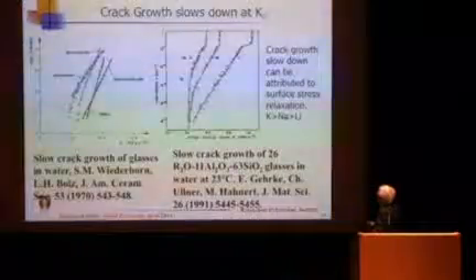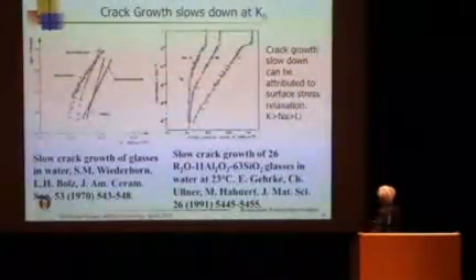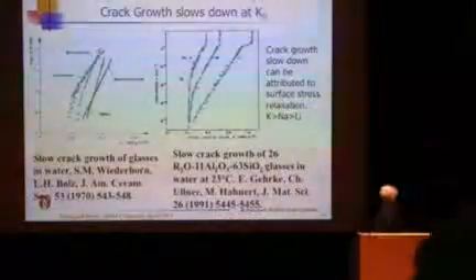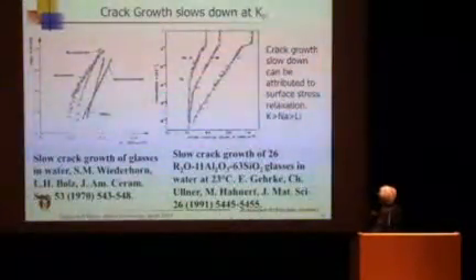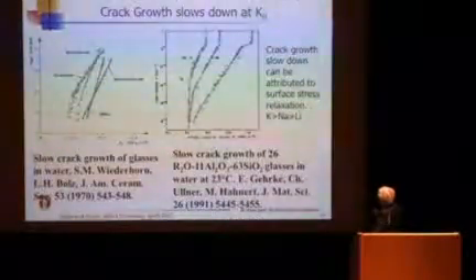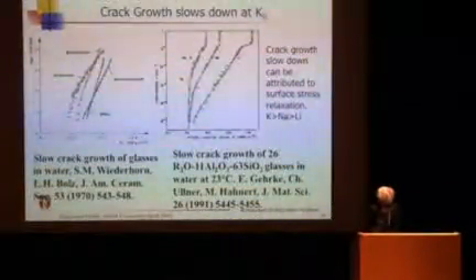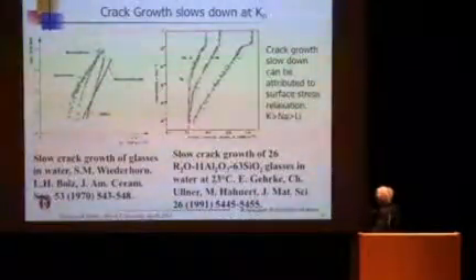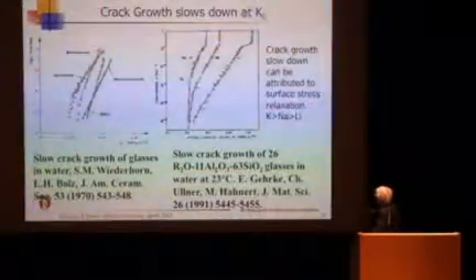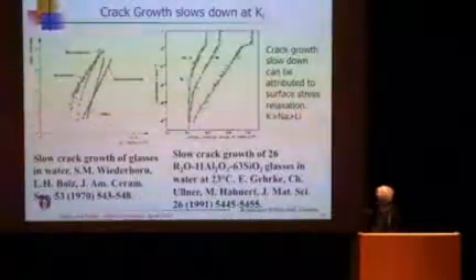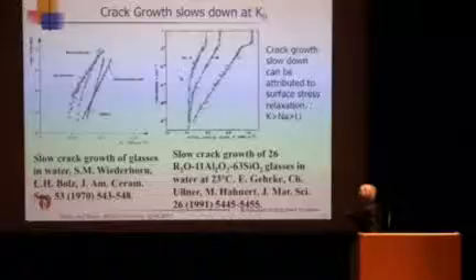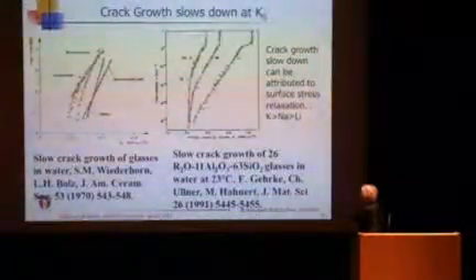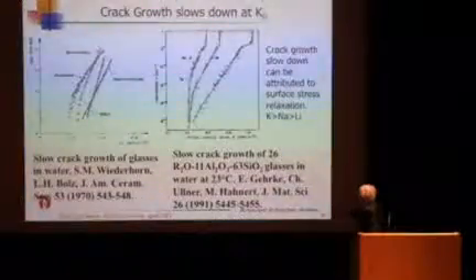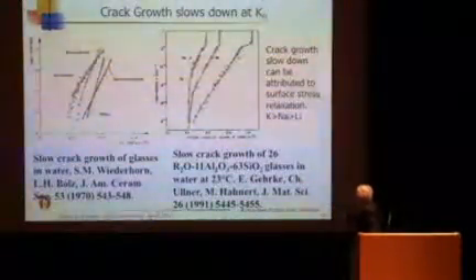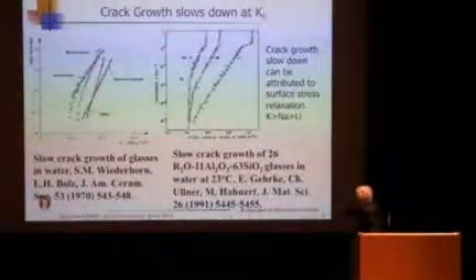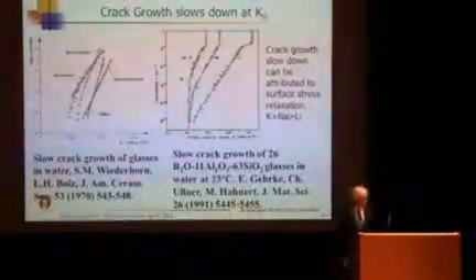That was our conjecture. And so these are the glasses: sodium, potassium, lithium aluminosilicate glass. Potassium glass seems to have a higher crack growth than lithium, but also tends to stop at a higher stress level. Around here, no more crack growth. Lithium around here, the sodium glass here. Soda lime glass shows this. Silica glass has not shown any bend like this. So you have to go to very long times, patiently, with slow crack growth, or you go to higher temperature to see the phenomenon.